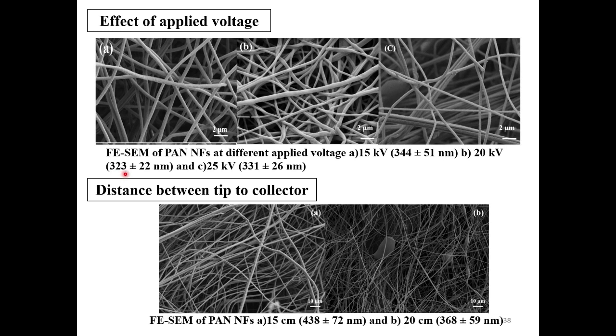If we again balance the concentration or viscosity of the solution and moderate the voltage, in the range between 15 to 20 kilovolt, we can again have a very controlled size of fiber. And when we talk about the distance between the tip and the collector plate, if we go for 20 centimeter, it gives 368 nanometer size of the fiber. It means the travel distance should be the maximum one, and then fibers are formed very fine, up to 368 nanometer.